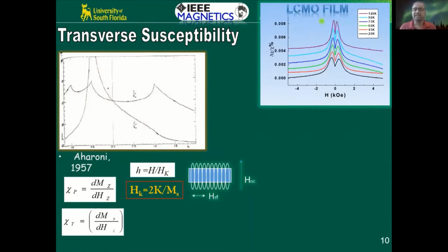This is for a manganite film. Because it's a thin film, the axes are well defined, the anisotropy is well defined, so you can see the peaks are very sharp. You can find out what the anisotropy field is, and from that, putting in the geometric factor, you can calculate the anisotropy constant, and everything goes well.